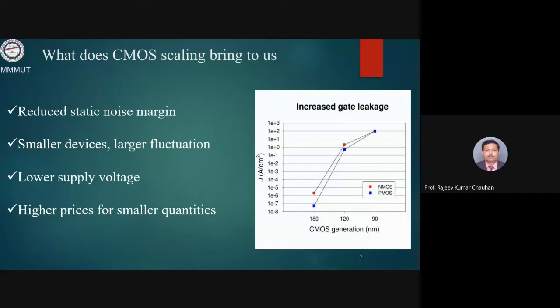And in the whole development of size reduction, one of the key components was the design of CMOS circuits. If one goes into the literature on MOS growth in the late 60s, from 67 to 71, they will find that suddenly everyone at the international level thought that circuits could not be designed using MOS. The reason was that a space satellite was sent at that time by the US, and it suddenly stopped working. Later, when the failure of that mission was studied, they found that the device was responsible. There was a sudden power failure, and the reason was ionizing radiation. No one had predicted that radiation can damage.